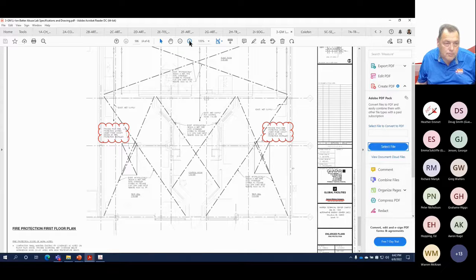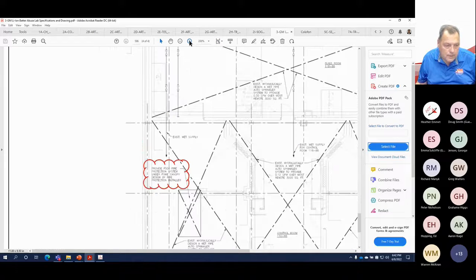And I suppose if I blow this up a little bit, we can see that we're providing an F500 fire protection system under the flume. So we did a design here using a sprinkler density of 0.2 gallons per minute per square foot, a proportioning rate of 3%. And this was installed by